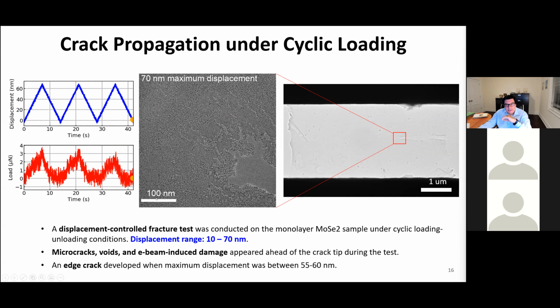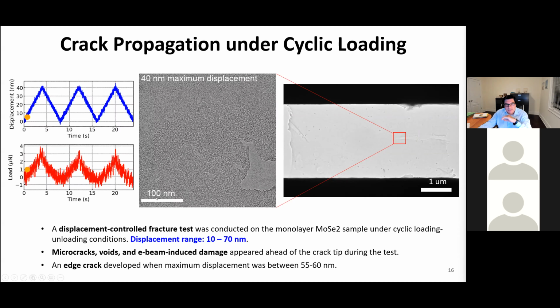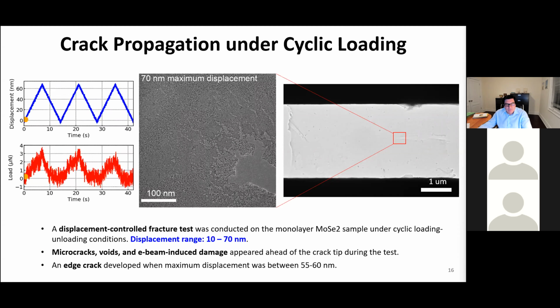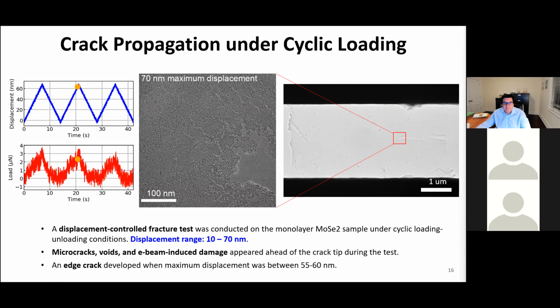So I will run this movie again, and I'll let you observe that. As you see, this is when the amplitude was 40 nanometers. This is when it was 50, so that you saw a little shift. And then when it's 60, you see the crack opening and some of the morphology of the crack evolving.